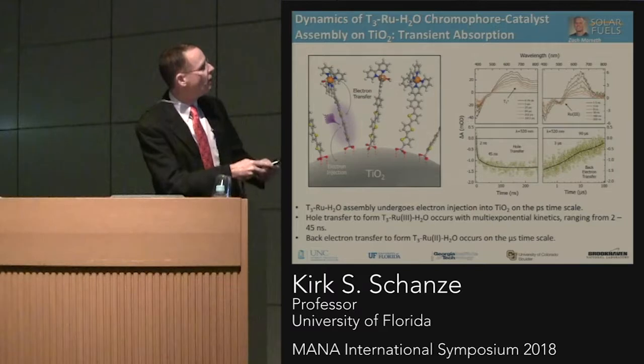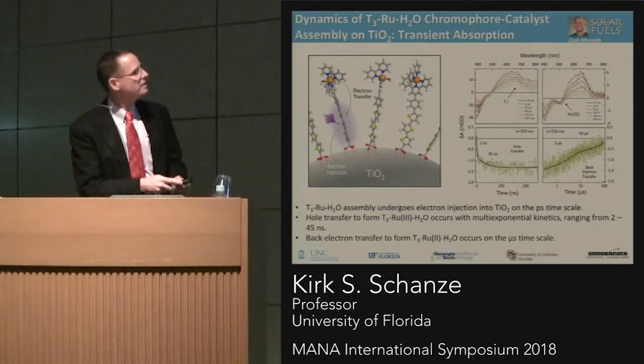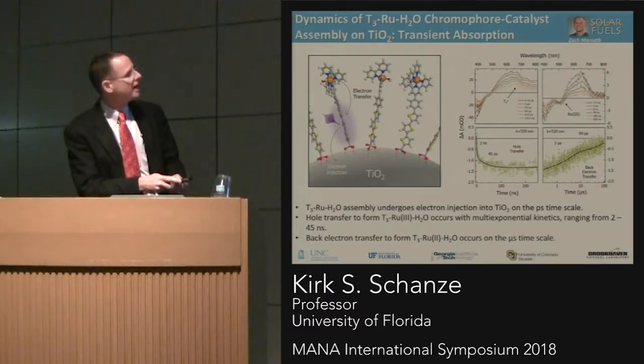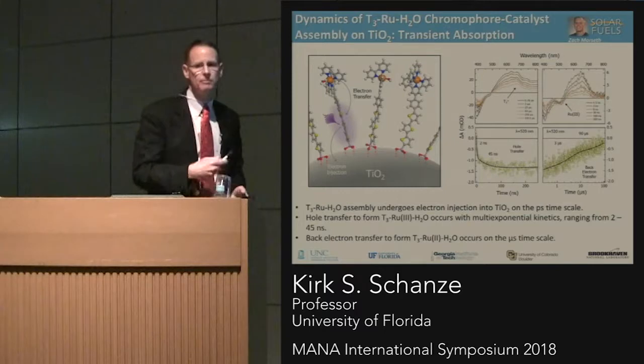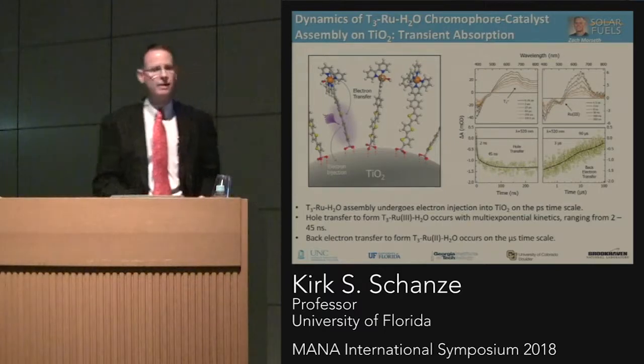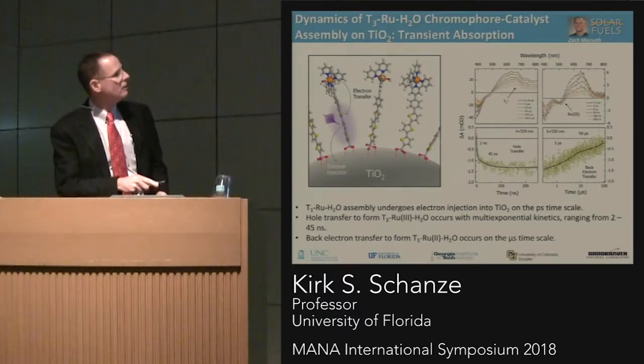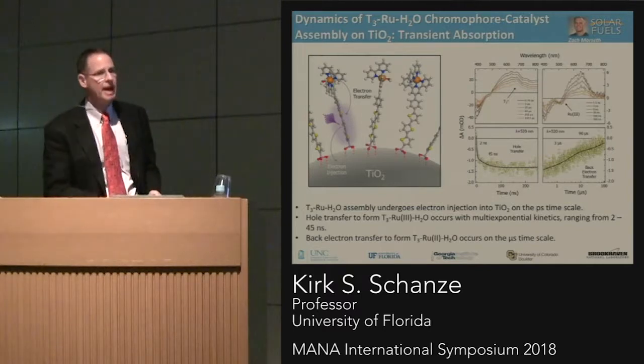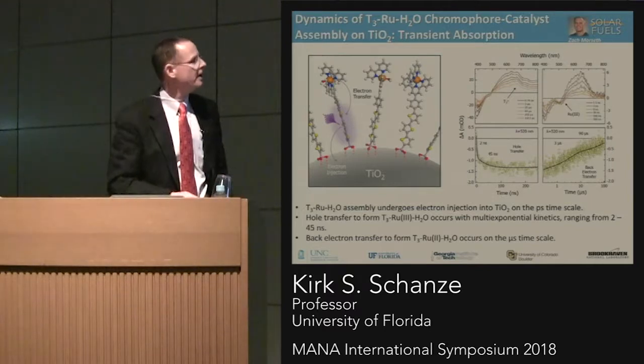That creates a hole on the thiophene, and then on a time scale in the microseconds, you see a second electron transfer, which then oxidizes a ruthenium unit, bringing it ready to do an oxidation step. So we know quite a lot about the photodynamics of these systems on the interfaces.